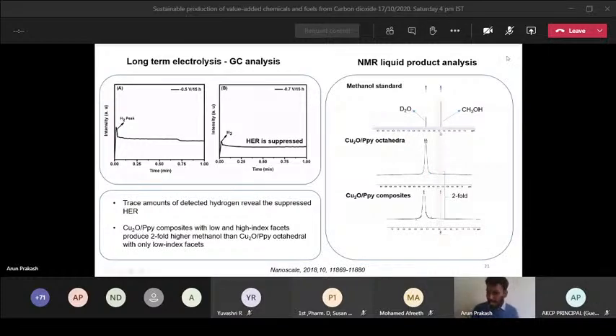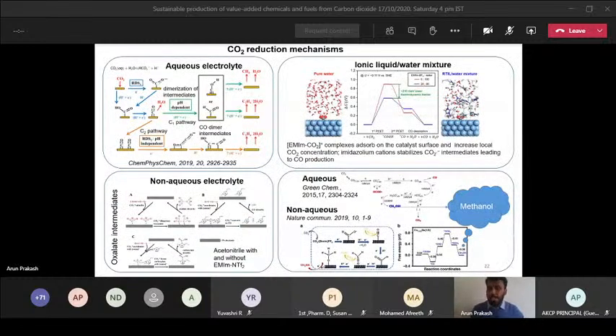And there are several mechanisms for CO2 reduction. You can look into the literature, and you can understand more about what is really happening at your electrode-electrolyte interface during CO2 reduction. But quickly to sum up, the mechanisms occurring in an aqueous electrolyte, an ionic liquid electrolyte and a non-aqueous electrolyte are totally different, so you have to bear this in mind. Every intermediate formed has a rate determining step, and we have to consider this, and also the local pH changes have to be considered.